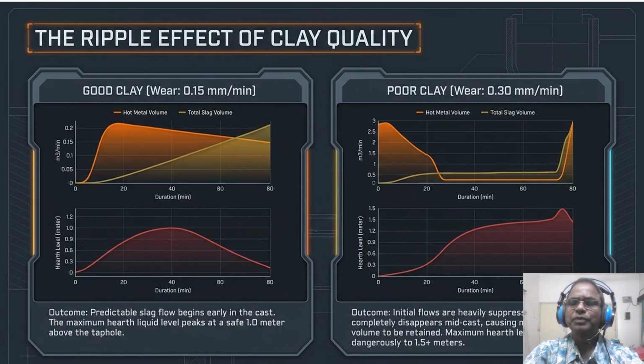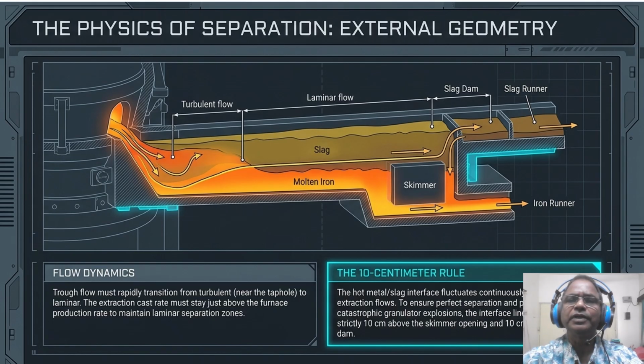Once the iron leaves the furnace, we must manage the transition from turbulent to laminar flow. Near the taphole, the flow is turbulent and chaotic. By the time it reaches the skimmer, it must be laminar. To ensure perfect separation and prevent a catastrophic granulator explosion, the hot metal slag interface line must remain strictly 10 cm above the skimmer opening and 10 cm below the slag dam.